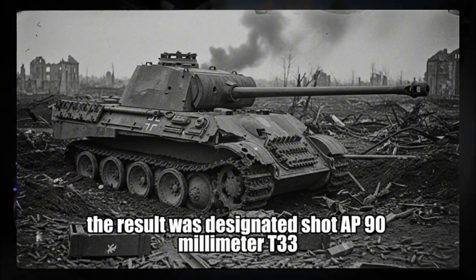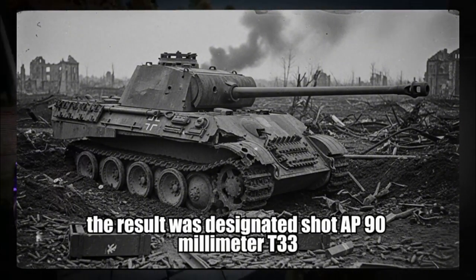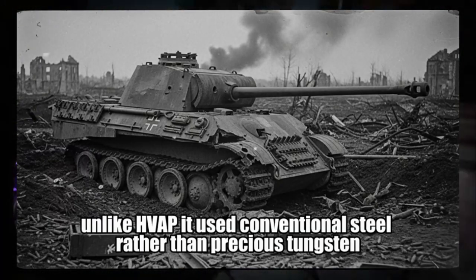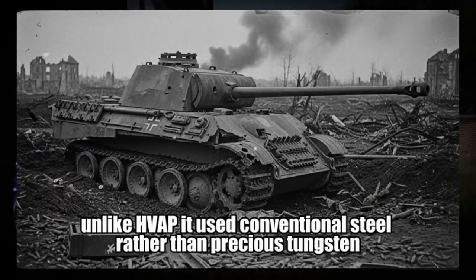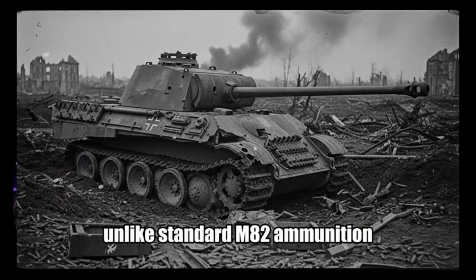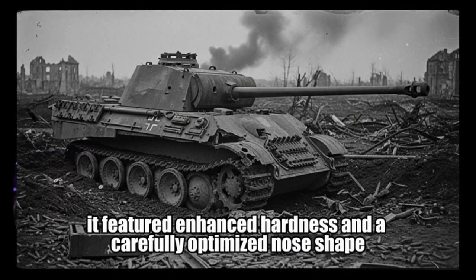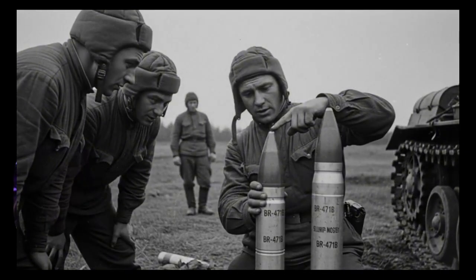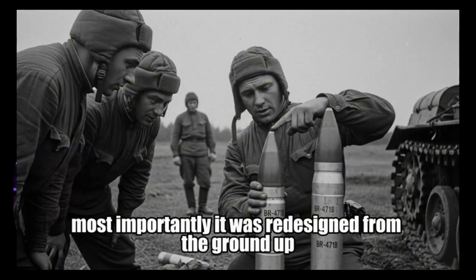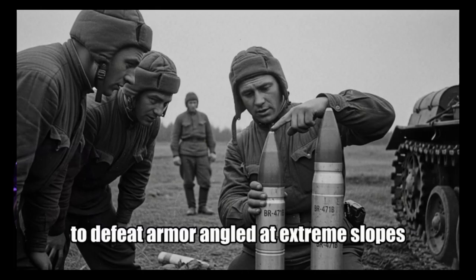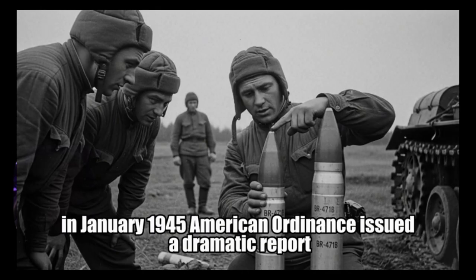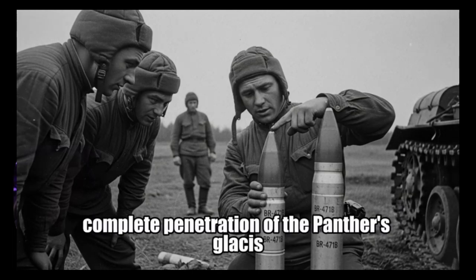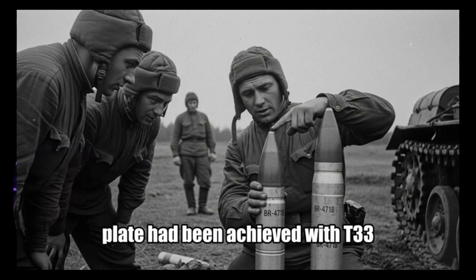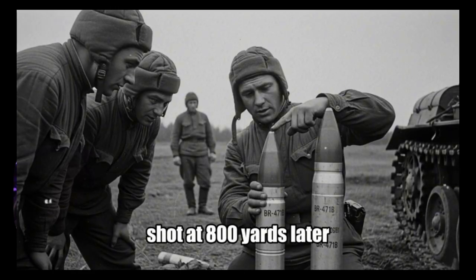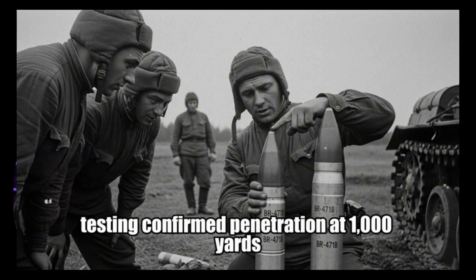The result was designated Shot AP 90mm T-33. Unlike HVAP, it used conventional steel rather than precious tungsten. Unlike standard M82 ammunition, it featured enhanced hardness and a carefully optimized nose shape. Most importantly, it was redesigned from the ground up to defeat armor angled at extreme slopes. In January 1945, American Ordnance issued a dramatic report. Complete penetration of the Panther's glacis plate had been achieved with T-33 shot at 800 yards. Later testing confirmed penetration at 1,000 yards.